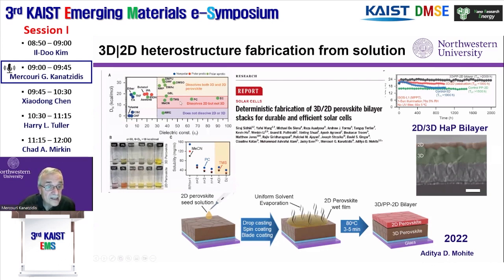And here we categorize them in these regions. So below the dielectric constant of 30, all these solvents, ether, butanol, isopropyl alcohol, ethanol, acetone, and so on, they can coordinate to lead, for example, but they don't have enough dielectric constant, so they don't dissolve the 2D. Toluene and so on, these are low anyway, so they don't dissolve. Over here, you have high dielectric constant, but low donor number. You also don't dissolve 2D or 3D. And if you have a little bit higher donor number and high dielectric constant, like acetonitrile, propylene carbonate, and so on, you can dissolve the 2D, but not the 3D.